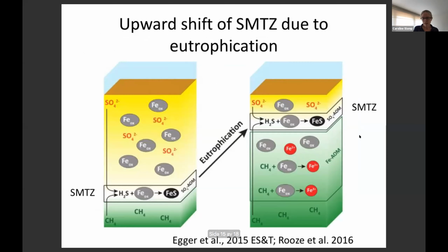Next slide, please. Now, why is this so important at this site? Well, one of the things we think is that this is an oligotrophic area, and this has become recently more eutrophic. Organic matter has come in, and this sulfate methane transition zone has shifted upwards. And now the sulfide-free sediments are much closer to the sediment-water interface. So this whole zone where you have a lot of iron and there's no sulfide has come much closer to the sediment-water interface. And in this zone, we have a lot of iron reduction going on, possibly also through a process with methane. And we have a lot of phosphate that's being released from the iron oxides that is actually diffusing down and reacting with this iron. And so this is why you have all this Vivianite at this location.